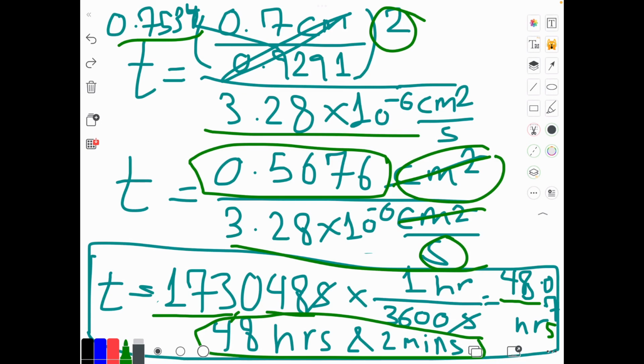There is another way to do this carburization process, by doing the reverse method, which means you have the time, the diffusivity, and the x value, which means you have the argument. You solve for the argument, you find the value inside the error function, inside that parenthesis. Now you have to do the interpolation to get to the value, and then maybe they ask you for Cx, maybe C0, maybe Cs. So you will find out what value you'll be getting, and you solve it out. So there's two ways to do this.